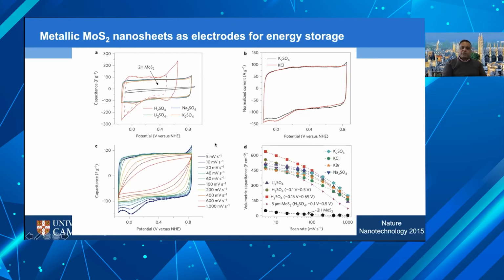And this is all due to the metallic phase allowing the ions to intercalate and deintercalate, and the high conductivity of the metallic nanosheets really boosts the kinetics. This narrow CV plot here is the CV for the 2H phase MoS2 nanosheets. You can see that there's very little capacity, which is also indicated here, where the 2H phase MoS2 volumetric capacitance is negligibly small in contrast to the 1T phase nanosheets.